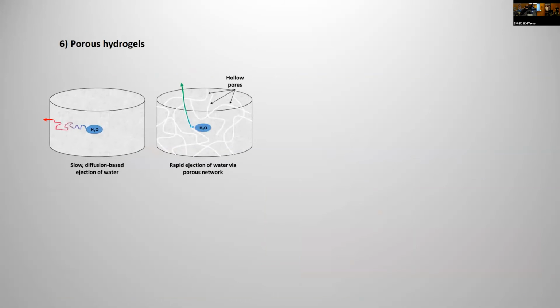Okay, so one of the issues when you look at these actuating hydrogels is based on the ability for water to get out of the bulk structure, because it has to go from right in the middle or wherever that interstitial water is to completely out of the whole thing. So if you have your usual hydrogel and you cross-linked it, if you look at the lovely cylinder I've drawn on the left, that water has to have a convoluted path to get out of the gel, and it takes quite a while. But if we can introduce these porous, empty pathways, all the water has to do is get to the closest one of those, and it has a free path right out of the hydrogel. So the reason for doing this is that hopefully we can speed up the actuation dramatically.